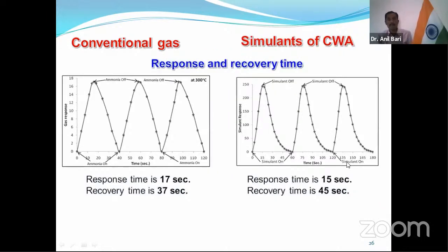Now, the response time and recovery time of that conventional gas. The first figure shows the response and recovery profile of ammonia gas. The response time is 17 seconds and recovery time is 37 seconds. While the second graph shows the response and recovery time of the chemical warfare agent simulant, that is DMMP, which gives a response time of 15 seconds and recovery time of 45 seconds.